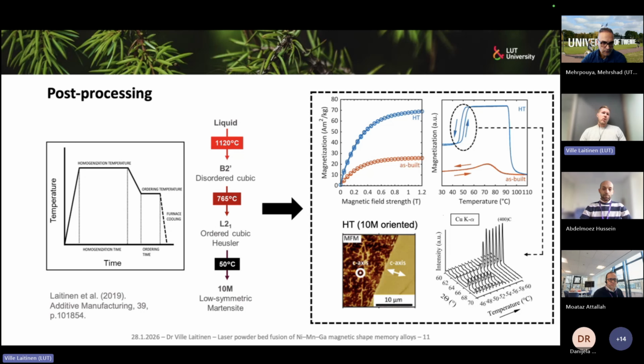We usually use a two-stage heat treatment. So we have this homogenization treatment, which is quite close to the solidus temperature of the material. The point of this treatment is to distribute those atoms equally within the geometry we have made. So basically, it's just diffusion. Depending on the times, it can be a couple of hours of treatment, or in the case of bigger parts, we might have up to a 12 to 24-hour treatment. We can also induce quite substantial grain growth in this treatment at that temperature range.